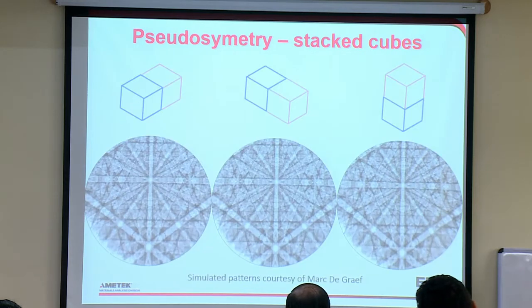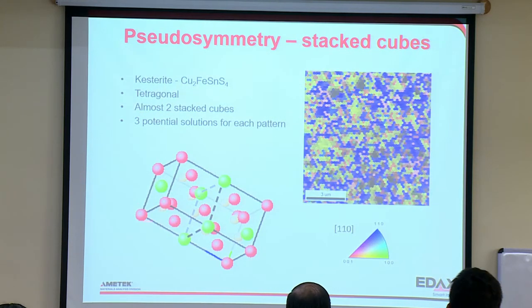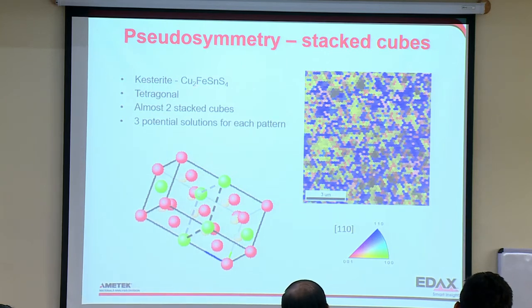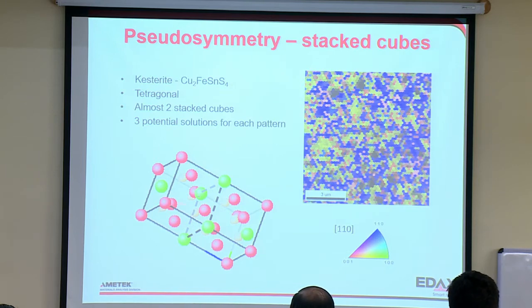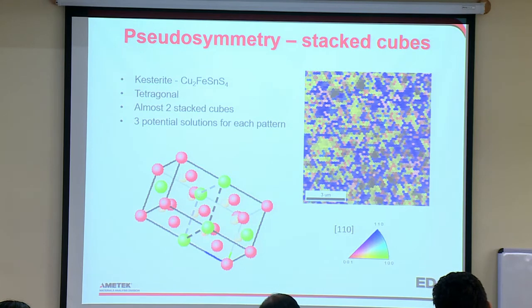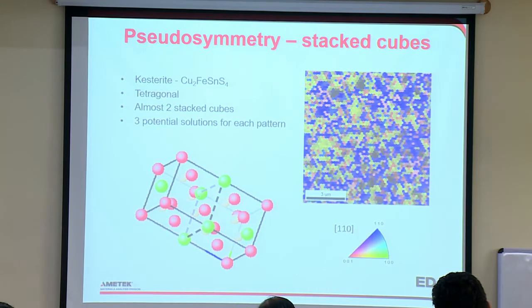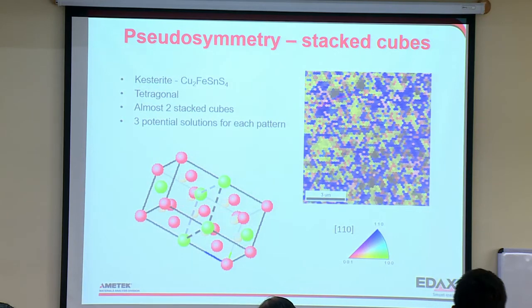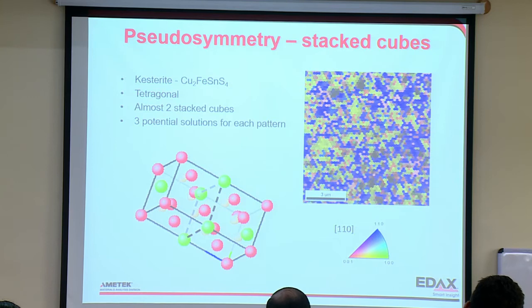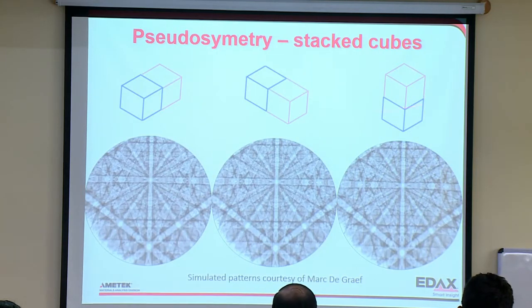So the stacked cube idea is this one. So this is kesterite, copper, iron, tin, sulfur. And I can't remember which is which. I think this is copper, and the red is copper, and the green is iron. And so this structure here is almost like two stacked cubes. And that's because under diffraction, the copper and the iron actually are pretty similar. And so indexing this material is really difficult. You get structures like this that are just completely nonsense. They're just random orientations. And that's because of this effect.